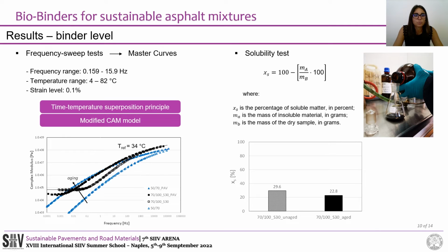From frequency sweep results, it is possible to see that lignin causes a significant change from a rheological point of view. First, an increase of stiffness is registered in the entire frequency domain, despite both binders were characterized by the same penetration rate, but the difference in stiffness is reduced after aging, which means that the biobinder seems to be less affected by aging. Moreover, a horizontal asymptote that is typical of modified bitumens or mastics appeared in the low frequency region, and it could mean that part of lignin probably acts as a filler.